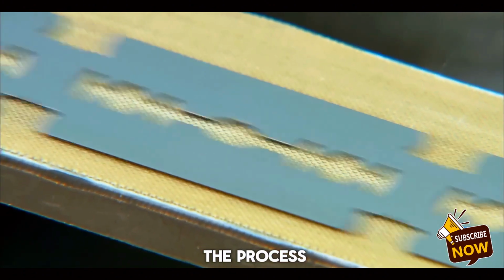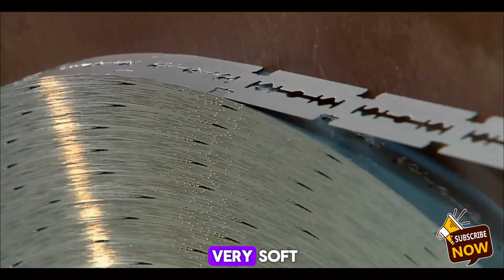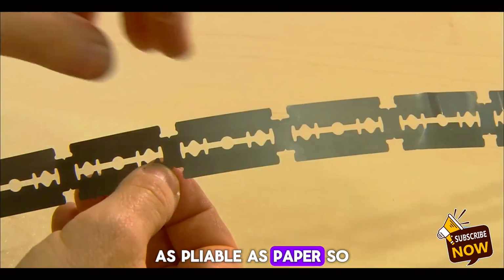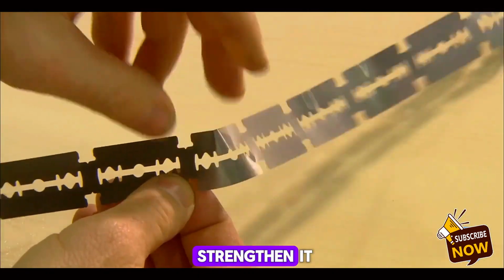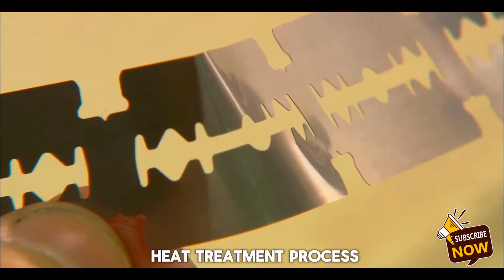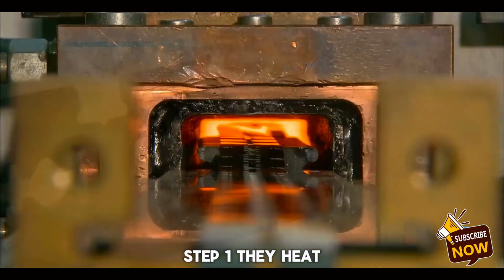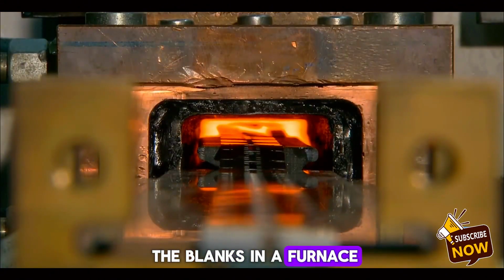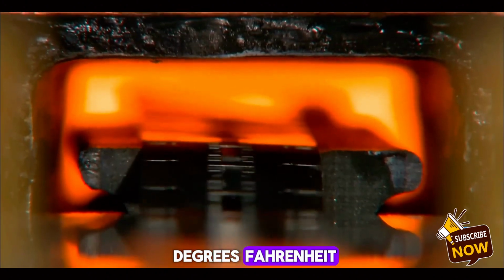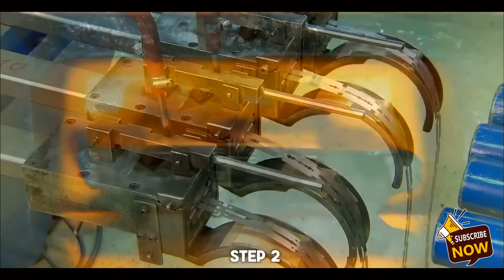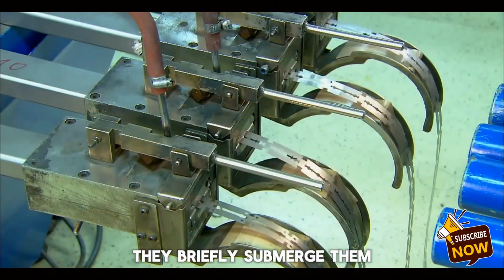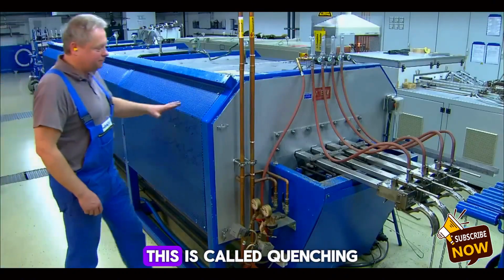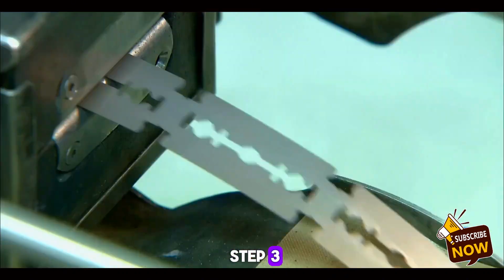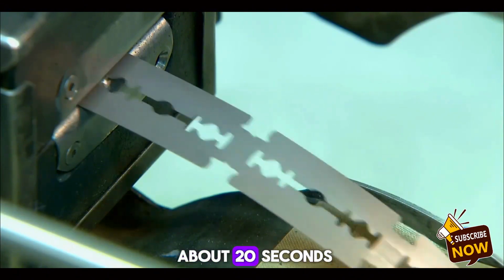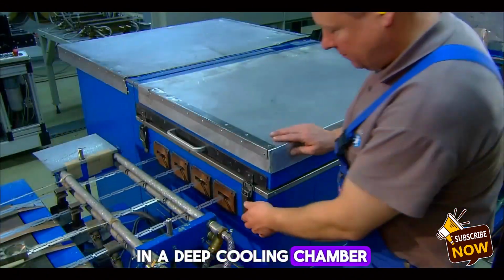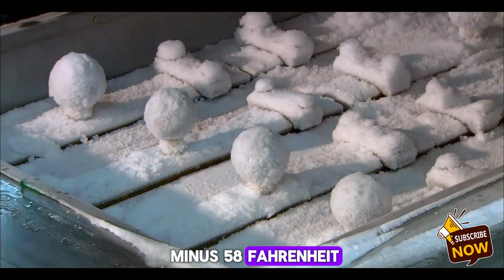At this stage of the process, the stainless steel is very soft, as pliable as paper, so they now harden and strengthen it through a 4-step heat treatment process. Step 1. They heat the blanks in a furnace to just over 2000 degrees Fahrenheit for about 30 seconds. Step 2. They briefly submerge them in cold water. This is called quenching. Step 3. They chill them for about 20 seconds in a deep cooling chamber at a temperature of -58 Fahrenheit.